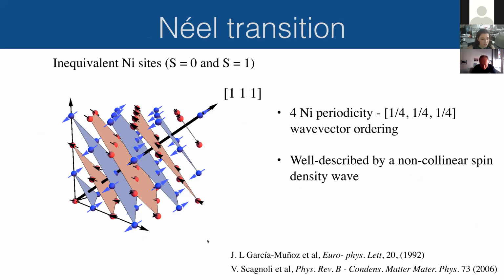Now, one of the other transitions is the magnetic transition in the nickelates. This is corresponding to an unusual antiferromagnetic ordering. Unusual because it's along the 1-1-1 direction, so it means you have to draw the magnetic ordering vector, you have to take the diagonal across the pseudocubic unit cell. And it has a periodicity of 4 nickel planes. So in the end, the antiferromagnetic wave vector is 1/4, 1/4, 1/4.